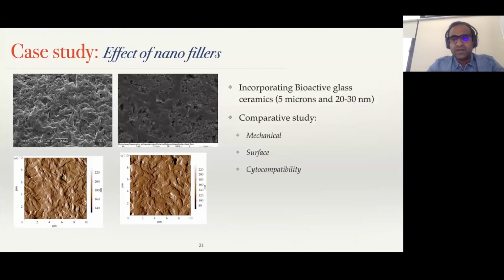Over here, we tried to find out the effect of using nanoparticles. For example, we tried to incorporate bioactive glass ceramics, which is analogous to hydroxyapatite in the bone, and the polymer is analogous to the collagen in the bone. What we found is that by reducing the size of these fillers, you get much better bone cell proliferation, better adsorption, better enhancement in strength, and better surface properties, so that the hydrophilicity and the surface energy are much more conducive for cell attachment.